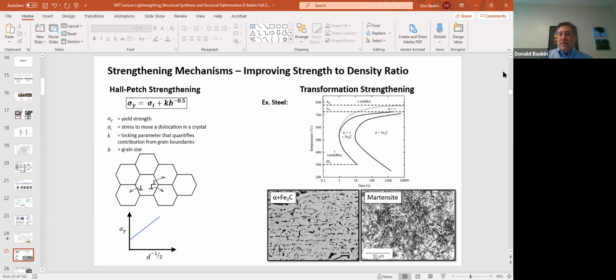The ferrite is body centered cubic. The austenite is face centered cubic. And then the martensite is body centered tetragonal. So these are the different phases of this material. The martensite, because it forms much smaller grains and has more carbon locked up in it, is much stronger than the ferrite. So this is a great example of transformation strengthening.